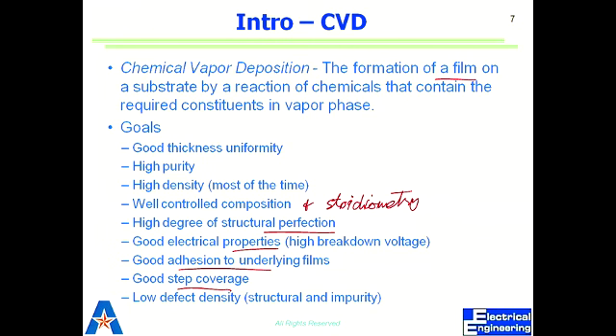So what do we want to get out of it? We want to get good thickness uniformity, which means that it's the same thickness everywhere. So if you have a full wafer, it should not have variation, or variation should be within tolerance. Yeah, so tolerance, we can't have it perfect always. What we can live with is, it should be within tolerance. Maybe 5%, 10%, depends on our process. And purity, high purity, not just in the material, but the byproduct shouldn't get incorporated itself. Right? So we want to have a recipe that gives us pure surface.